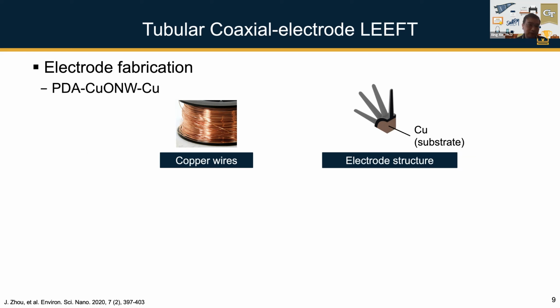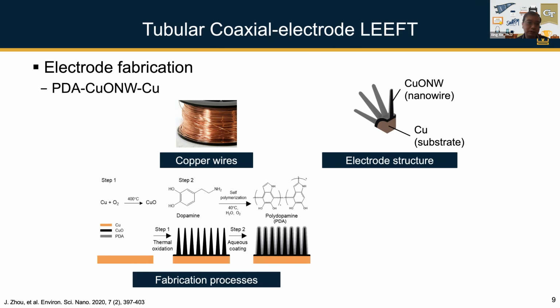It's actually very thin. The diameter of this copper is thinner than 100 micrometers, about 80 micrometers, so it's very similar to the thickness of your hair. It's a pretty thin and pretty long roll, a very low cost material. We do a one-step oxidization process. We heat it up in the atmosphere at a certain temperature, and then you will grow copper oxide nanowires on top of this copper wire.